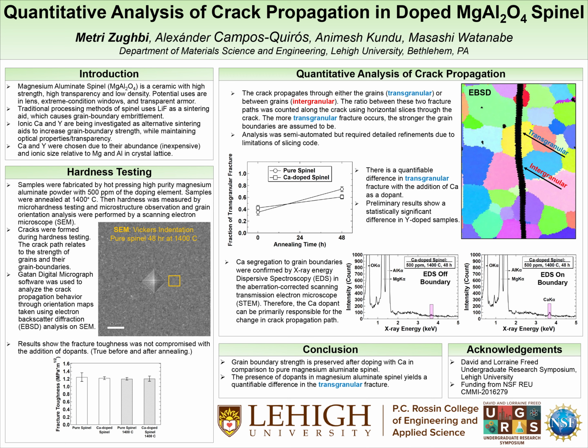As you can see with the line chart in the middle of the poster, even with 500 ppm of calcium, we see statistically significant differences among the propagation of each crack in the samples. And though not shown, changes were also observed in yttrium-doped samples. Lastly, to help ensure that the dopants were responsible for the change in crack propagation, energy dispersive X-ray spectroscopy, or EDS, was used in a scanning transmission electron microscope, or STEM, to determine that the element was found in much higher concentrations on the grain boundary rather than in the grain.